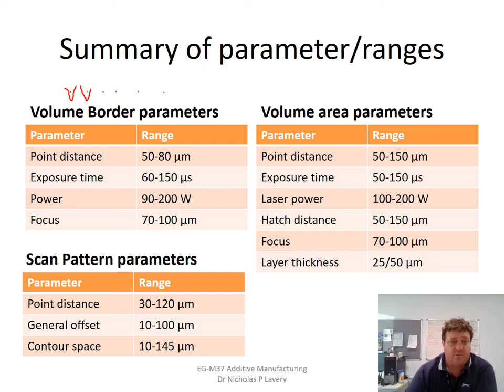This is actually for the volume border here, where I was pointing out. The volume area parameters are slightly different. We'll use slightly higher powers and slightly higher hatch spacings. But typically the layer thickness will be somewhere between 25 and 50 microns.